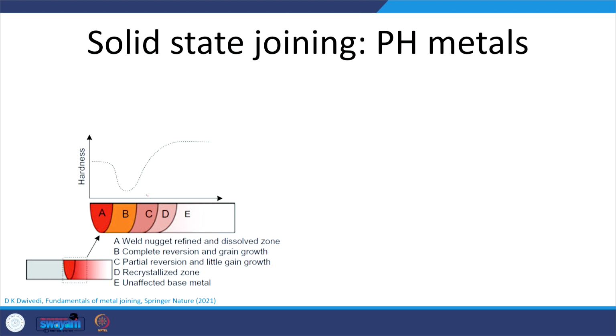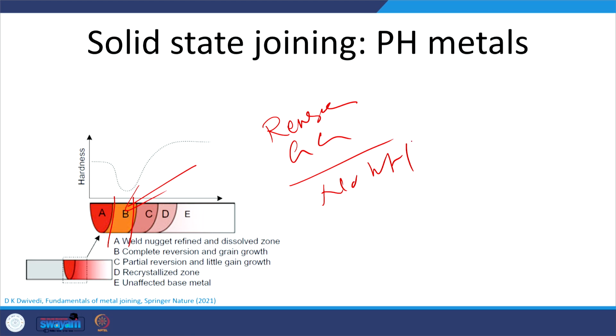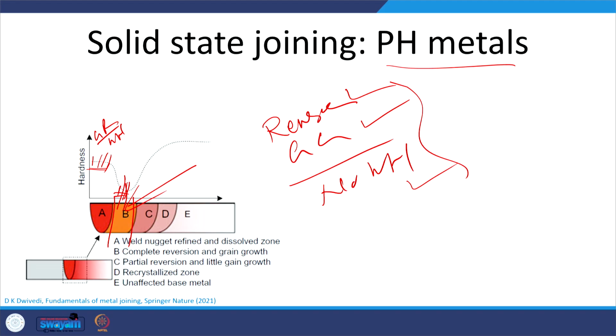in that area, which is significantly affected by the heat, there will be a severe drop of hardness, and that is attributed to complete reversion coupled with grain growth, with no work hardening effect whatsoever. That is why even in precipitation hardening metals we get slightly higher hardness in the nugget due to grain refinement and work hardening, but in the HAZ there is a significant drop due to the reversion, complete loss of precipitates coupled with grain growth, and no work hardening effect. That is why the minimum hardness zone is found in the HAZ of the precipitation hardening metals which are subjected to solid state joining processes